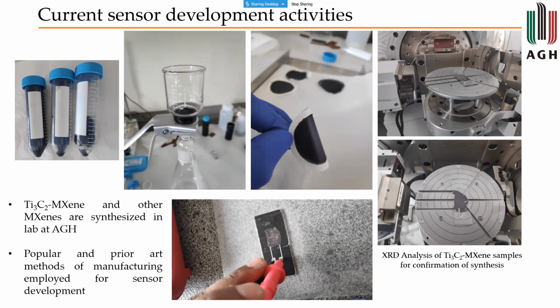here to test them out, is basically using the liquid form MXene, vacuum filtering them through the standard process we have, making the films out of them and drying it in vacuum to get the final devices that we make. So this is a sample which has glass fiber epoxy base, upon which we have a silver epoxy electrode being printed and then the sample attached to it.